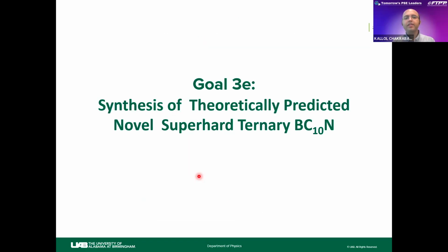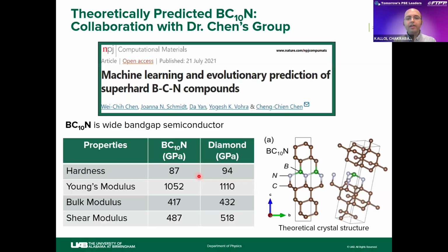The next one was synthesis of the theoretically predicted novel superhard ternary BC10N material. Dr. Chen's group predicted this novel superhard BC10N material. Why is it important to synthesize BC10N? As you know from the theoretical prediction, BC10N has a hardness around 87 GPa, which is comparable to diamond.